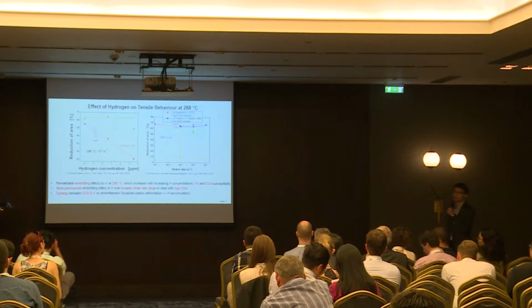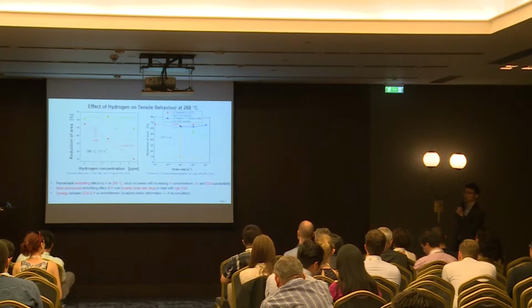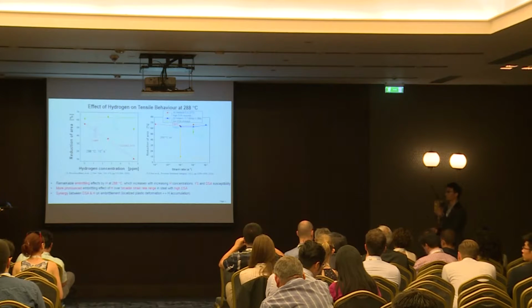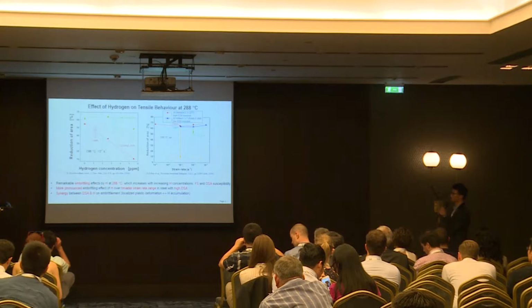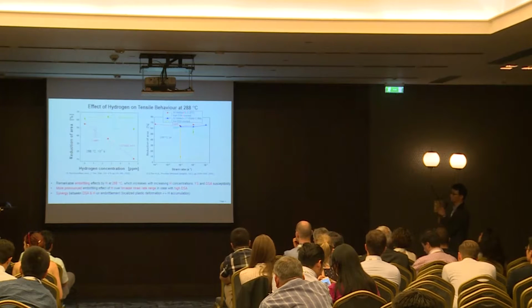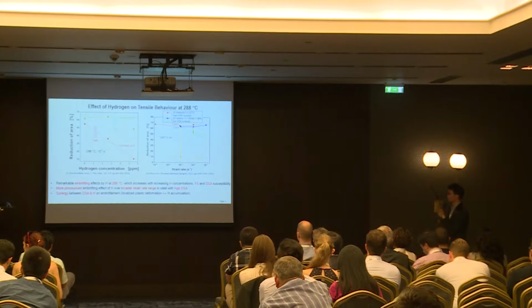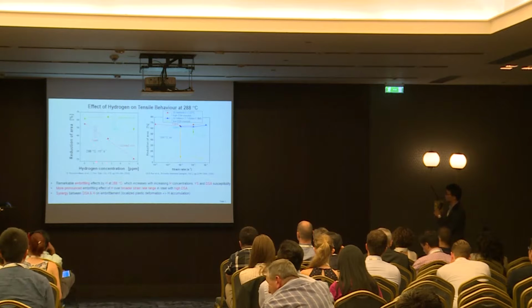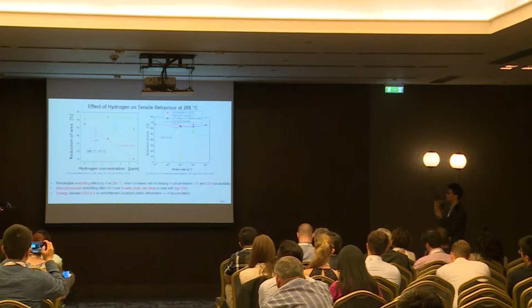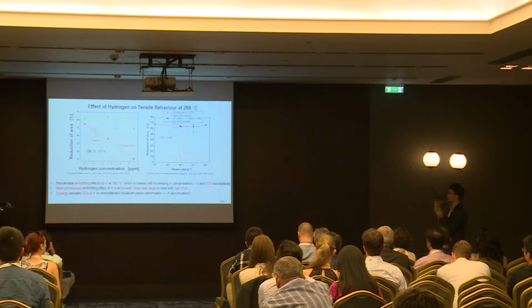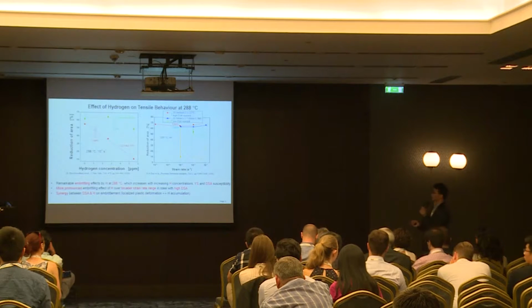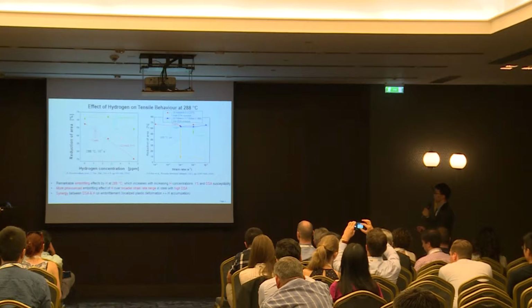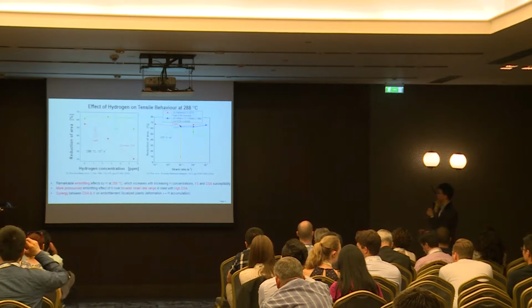The other thing is that hydrogen effects are usually thought to be absent at high temperature, for example 300 degrees Celsius. However, with some previous work in our group, it has been proven that even at a temperature of 288 degrees, hydrogen embrittlement is still possible. And the figure on the left describes the reduction of area with the increase of hydrogen concentration for two steels versus base metal. The second one is the heat treated one, which has a high yield strength. So it's quite clear that with the increase of hydrogen concentration or with a high yield strength steel, there's a remarkable embrittling effect of hydrogen.